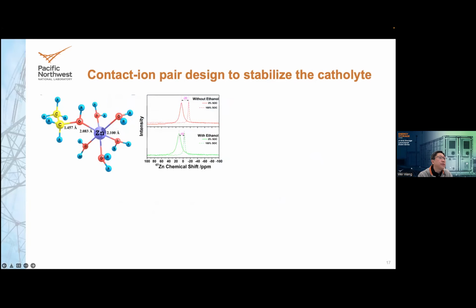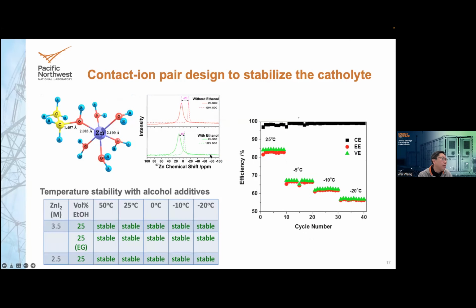The one we choose is a simple alcohol that we know will complex with zinc. After we add ethanol at 5 or 10% in the electrolyte, you can see the NMR signal change. This addition of simple alcohols can stabilize the zinc iodide electrolyte at quite low temperature and high concentration. This is the cycling performance.